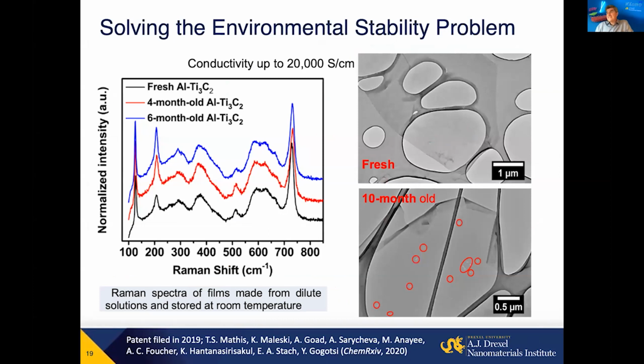Basically, I showed a slide. It used to be the fact. We know that it's not a fundamental problem. We know that surface stoichiometry and surface oxygen can protect MXenes. So these flakes have been single layer flakes in water at room temperature for 10 months. When they are assembled in devices, we believe definitely a lifetime of many years is possible. Of course, there are some other MXenes with lower stability, but again, I think it's a matter of optimizing the material, perfecting the structure, controlling the composition, and we'll have much more stable materials.